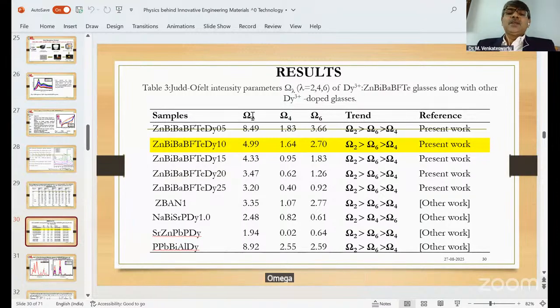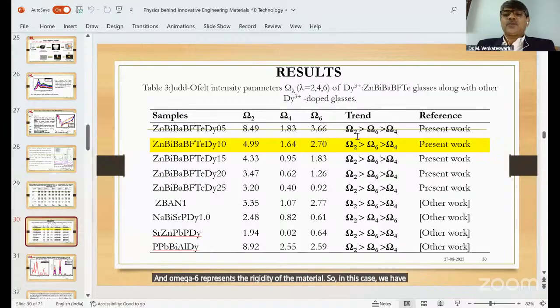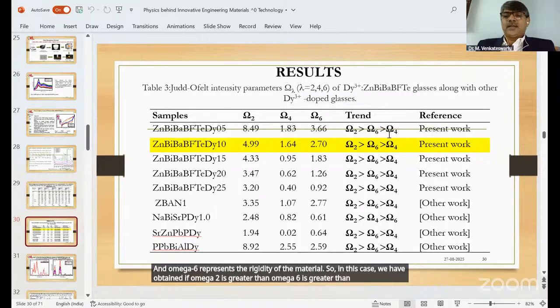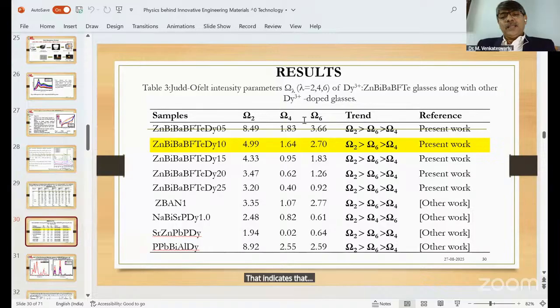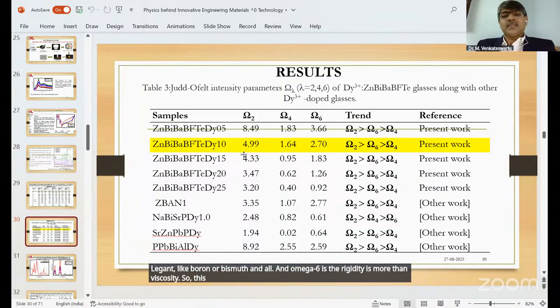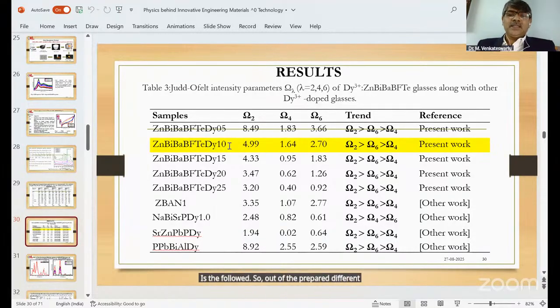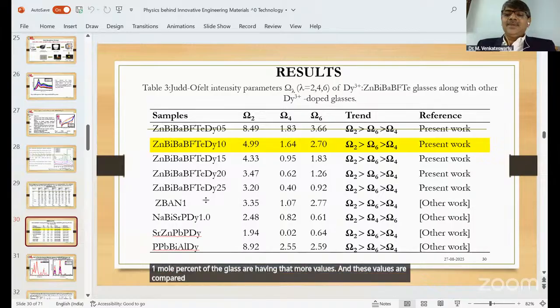Omega 2 represents the covalency nature between the rare earth and the surrounding ligands, omega 4 represents the viscosity of the material, and omega 6 represents the rigidity of the material. In this case we obtained the trend omega 2 greater than omega 6 greater than omega 4. That indicates the covalent nature between the rare earth ion and the ligands like boron or bismuth. And for omega 6, the rigidity is more than the viscosity. So this trend is followed. Out of the different mole percentages prepared, the 1 mole percent glass has the higher values. And these values are also compared with the literature.